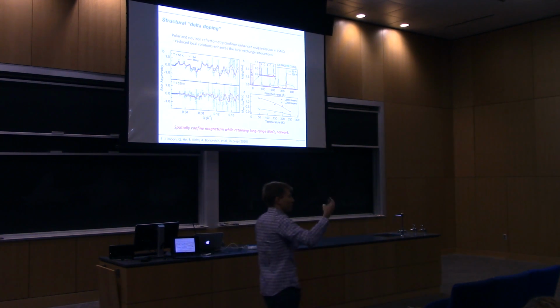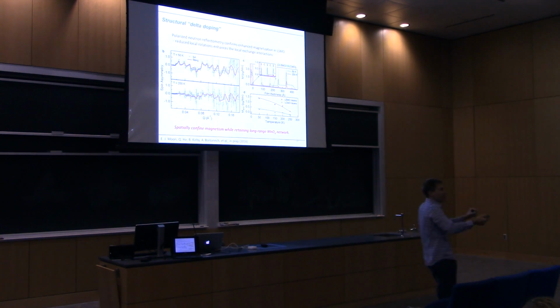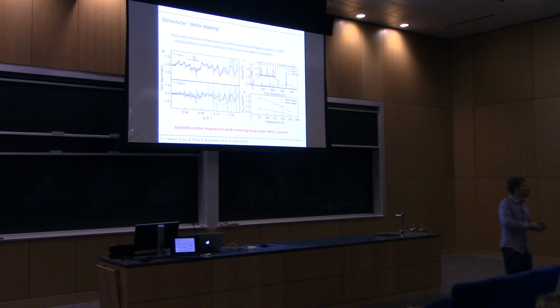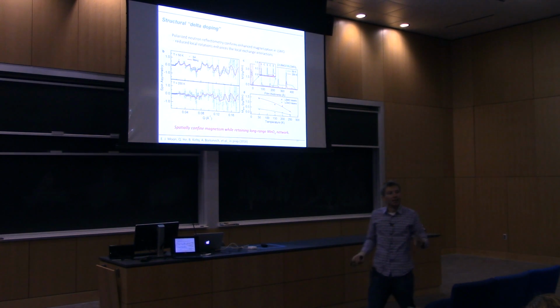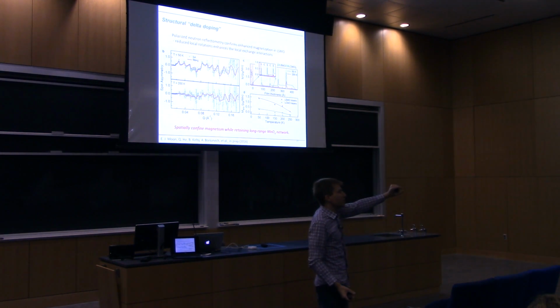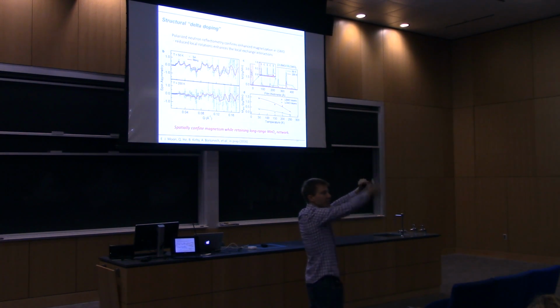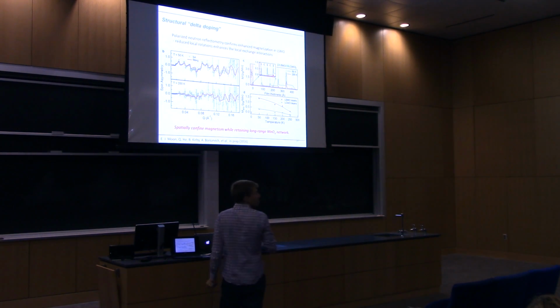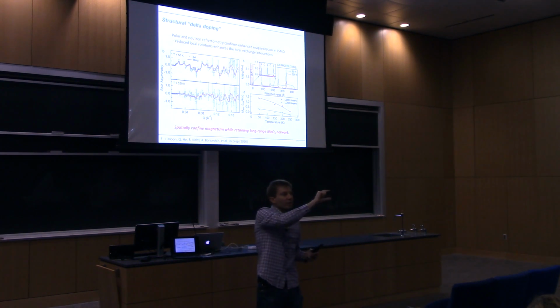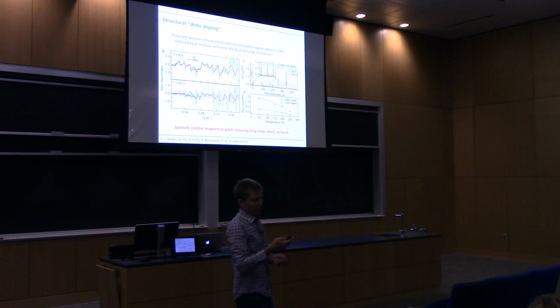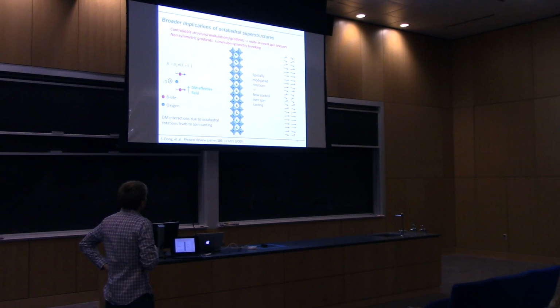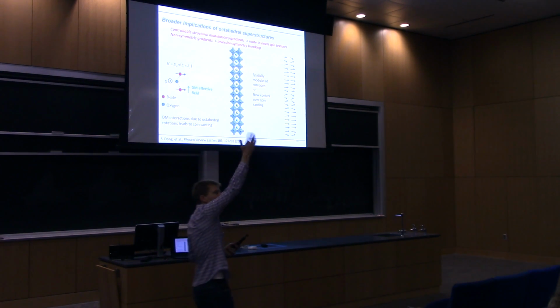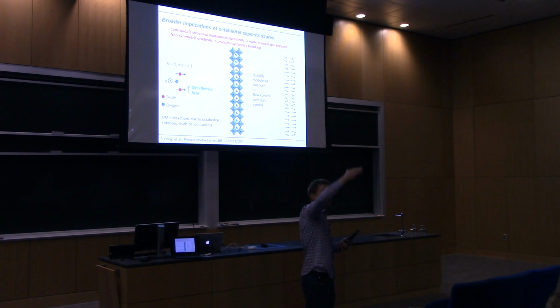And so normally if we want to take a perovskite and study how the magnetic properties behave in reduced dimensions, we need to make a very thin film, maybe just a couple unit cells. But that's a very different beast than the bulk because we have all these dangling bonds at the surface and interfacial bonds. But here, with this technique, where we put a material with reduced rotations inside a matrix that has large rotations, we maintain that MnO6 3D network, where we just get this thin region with enhanced itinerancy and enhanced magnetic properties. All right. The other thing that one could point out is that if we have control, we can realize these spatially varying modulations, and we can dial in these modulations of the octahedral rotations.